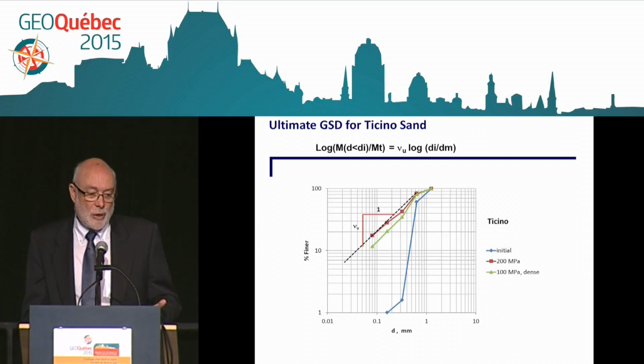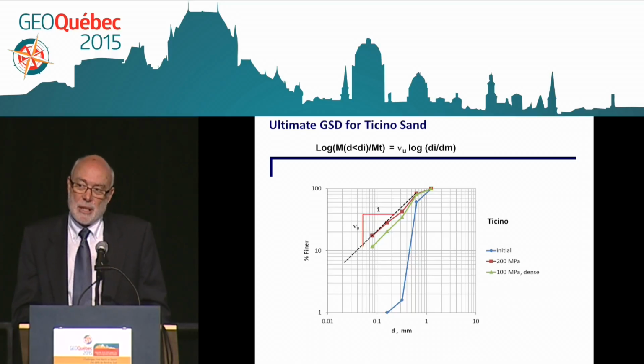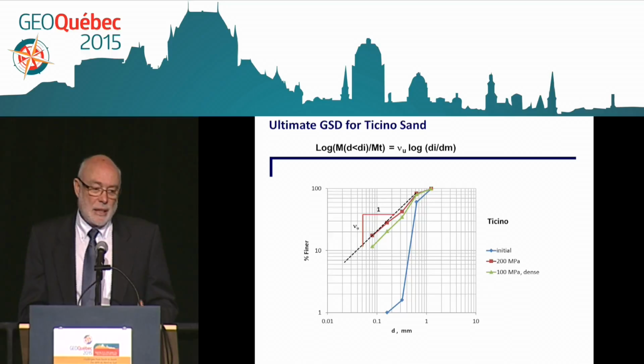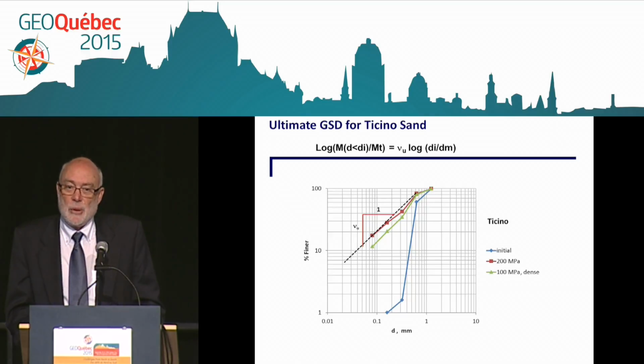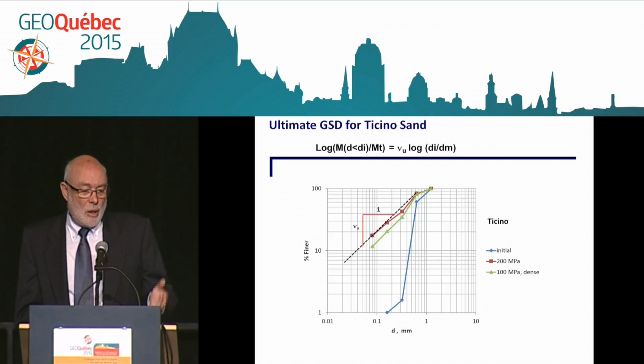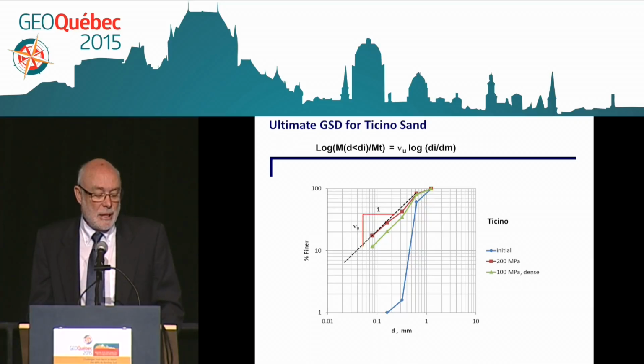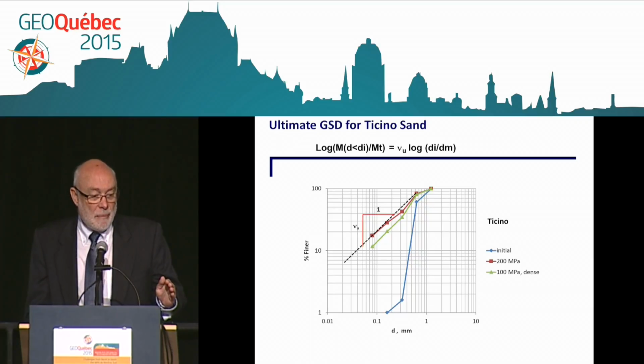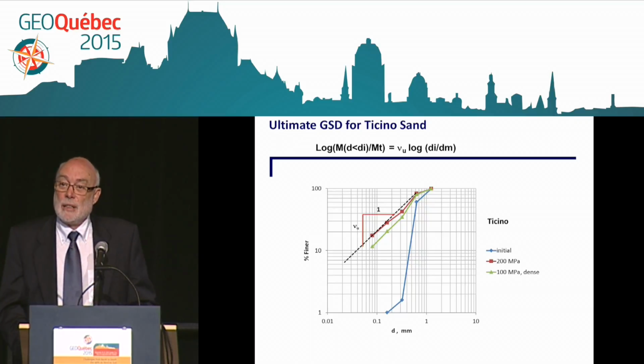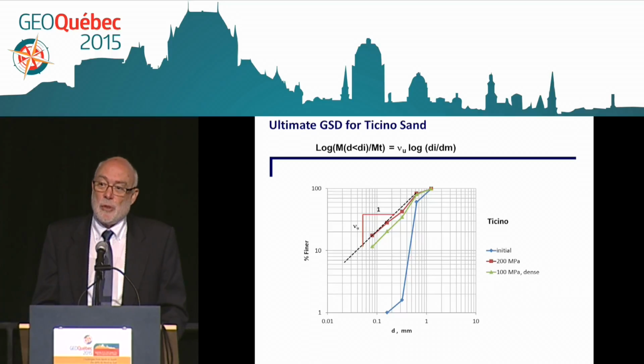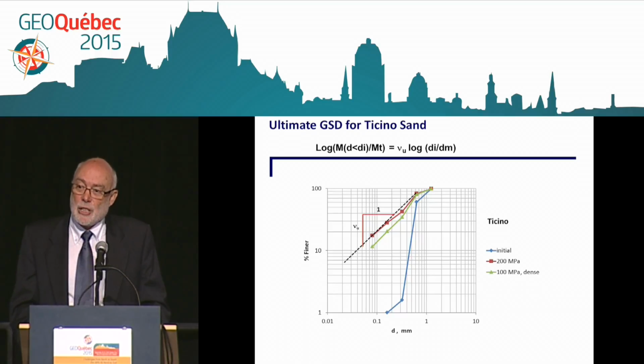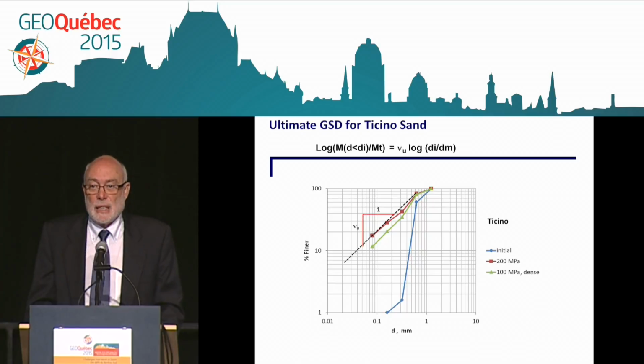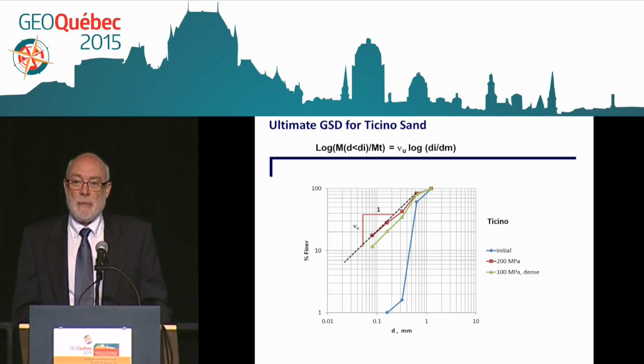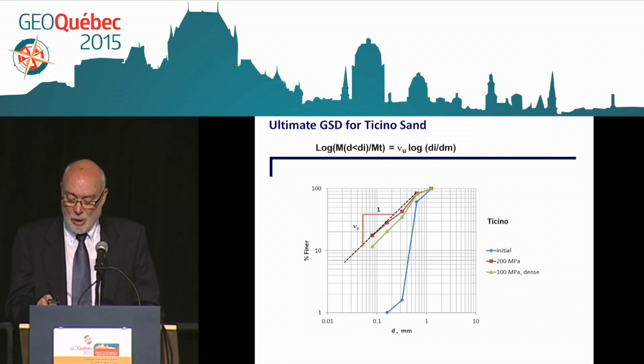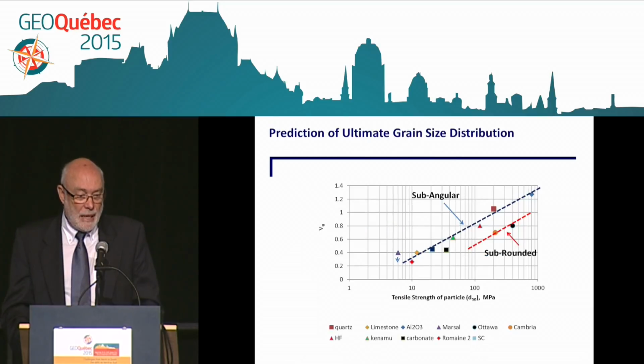So what you have to do is to change a bit your habits, and instead of using an arithmetic scale for percent finer, we use a log scale, so log-log, and you see that the ultimate distribution here in red is a straight line in such a plot, and we take the slope of that line as the representation of the ultimate grain size distribution. So one parameter, and we have the grain size distribution curve quite easily.